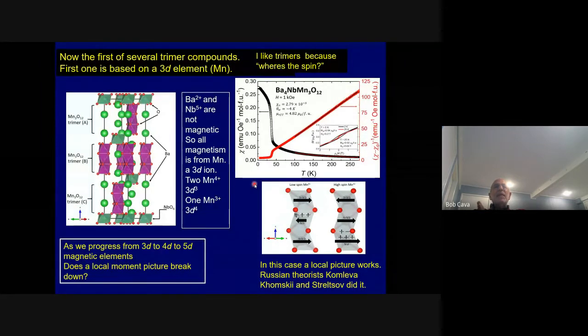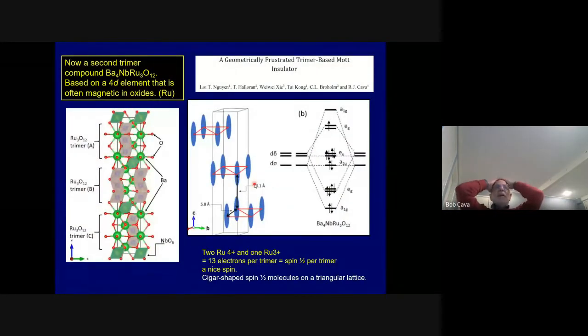But this was not enough to deter me, so we made another one, barium 4, niobium, Ru3O12. Now ruthenium is our magnetic element that is based on 4D electrons, so the orbitals are sticking out more. So you expect this thing to be more strongly hybridized than in the manganese case. In this one, again, you get ordering of the ruthenium here and the niobium in the octahedra here. Niobium 5+ is non-magnetic. So this is now a triangular lattice of cigars. If you think about this thing, it's a little molecule. You can draw its molecular orbitals, and it has a spin of a half in a molecular picture of this thing.